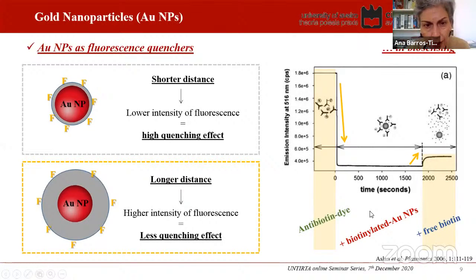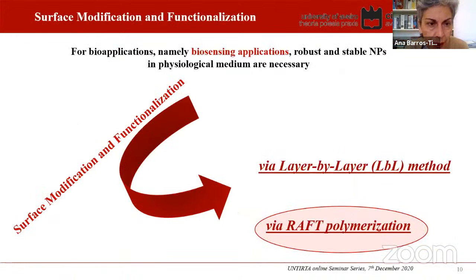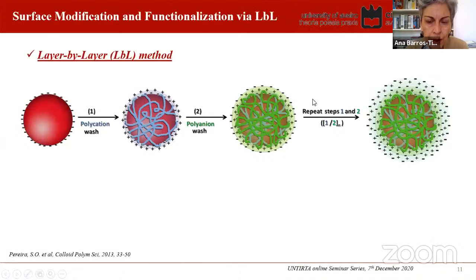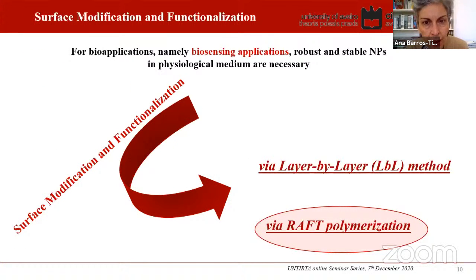So with this in mind, we then moved on to attempt the preparation of gold nanoparticles for biosensing applications. But for this, you need stable nanoparticles in physiological medium. Therefore, we need to carry out surface modification and functionalization. This can be done by a variety of methods. Amongst the many methods available, two are particularly well known. One is via layer by layer method, and the other one is encapsulation of the nanoparticles